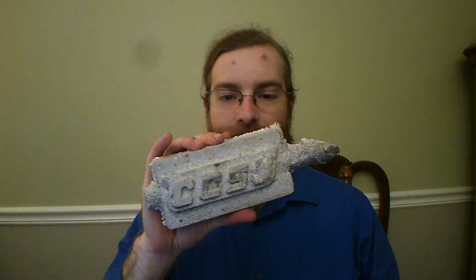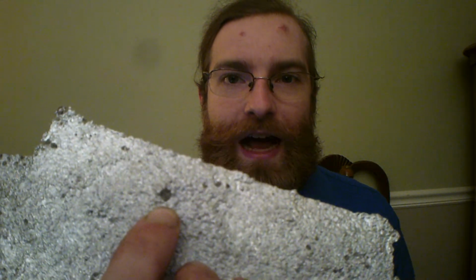So from the first round, we came up with this. Now, I will readily admit, the sand I was using was way too dry. I should have stopped immediately and retempered it, and I realized that almost immediately, but gosh darn it, I wanted to get through that project. So I used sand that was too dry, and my surface finish definitely suffered as a result. I also had many more sand inclusions, little pockets like that are actually sand embedded in the casting. So in order for this to be shippable, that would have to be blended out somehow.